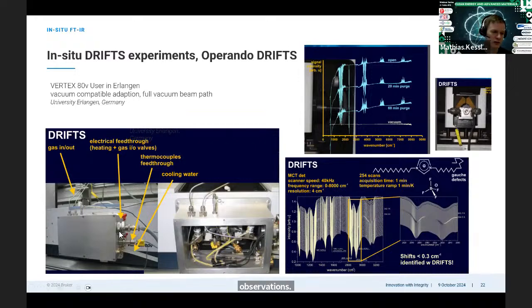It's also possible to do the measurement not only in the purged sample compartment of the vacuum spectrometer, but we can also use a special front cover, and then we have the complete setup under vacuum. With such a setup, we can get a very good baseline. If we compare the baseline of the measurement with the open system, with a purged system for 20 minutes and for 60 minutes, and with our vacuum measurement, we can get rid of all the spectral bands which are coming from water vapor and CO2 in this case.